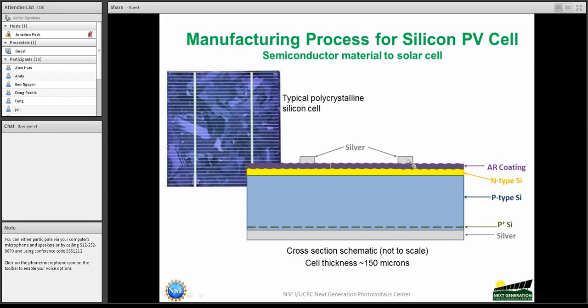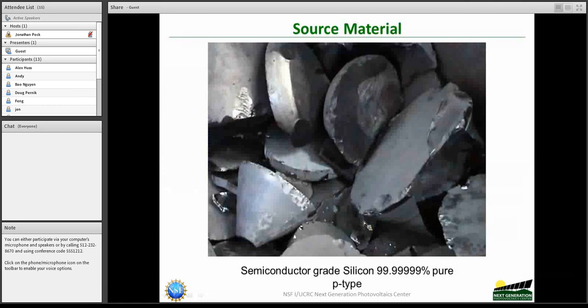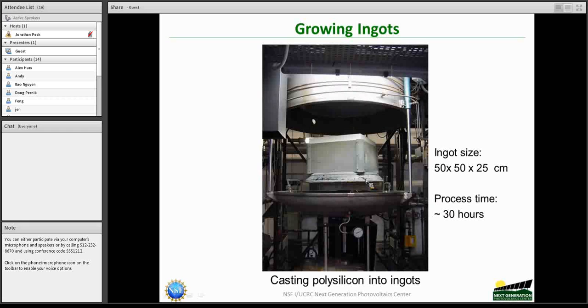Voltage and current comes from the top silver contact to the bottom silver contact, and the total thickness is in the neighborhood of about 150 microns or so for the whole cell, and you need that thickness to convert most of the sunlight to electricity. The starting material for silicon is semiconductor grade silicon, which is usually seven nines pure. And in this particular case, you start with P-type material. Now, there is quite a bit involved in making this material itself, but I'm not going to be discussing this in this talk. So once you have the material, usually it is made into an ingot, and the typical size of the ingot is about 50 centimeters by 50 centimeters by 25 centimeters. So you're looking at about 2 feet here in terms of dimension.